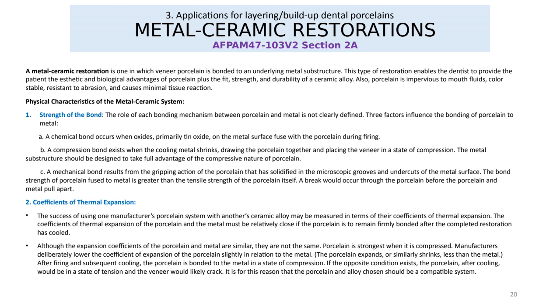A mechanical bond results from the gripping action of the porcelain that has solidified in the microscopic grooves and undercuts of the metal surface. The bond strength of the porcelain fused to metal is greater than the tensile strength of the porcelain itself. A break should occur through the porcelain before the porcelain and metal pull apart.